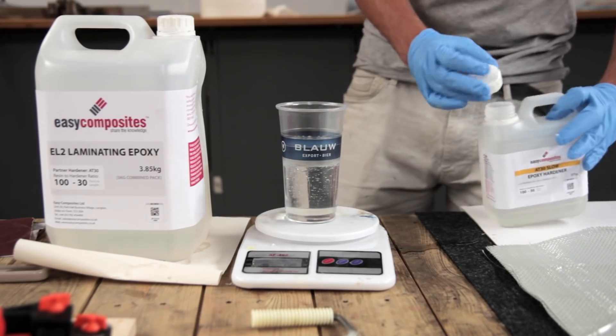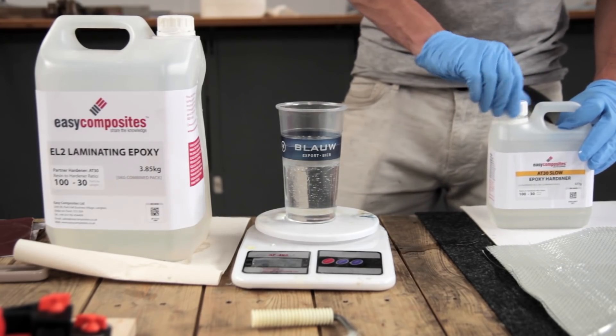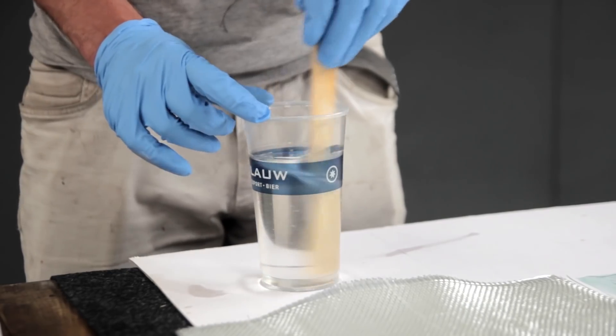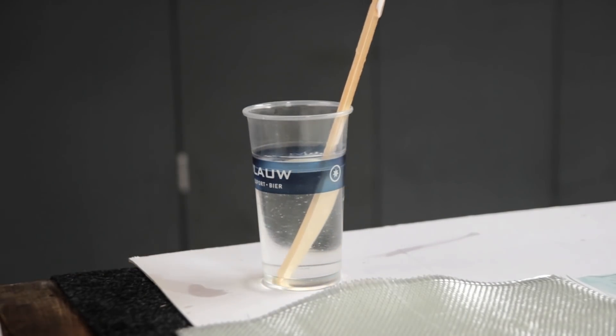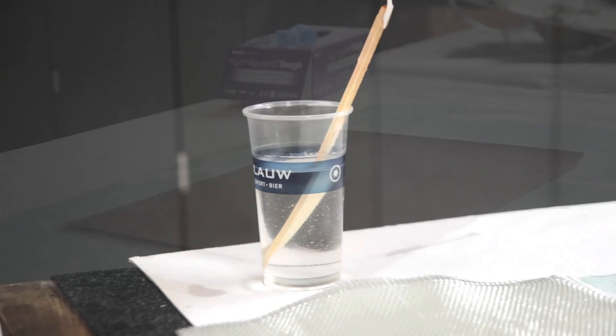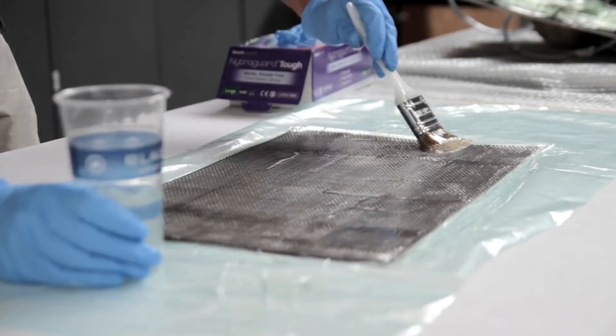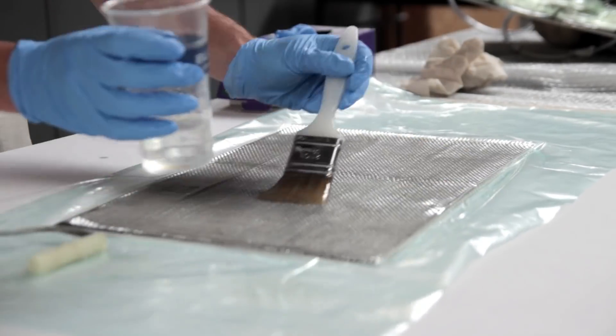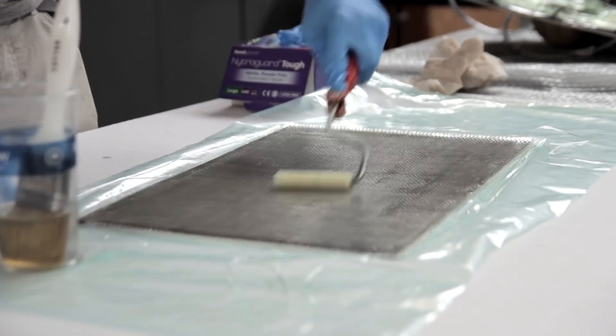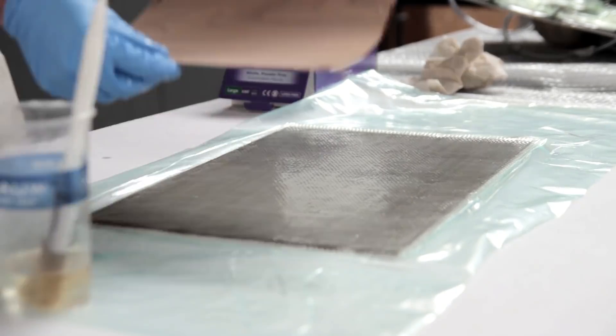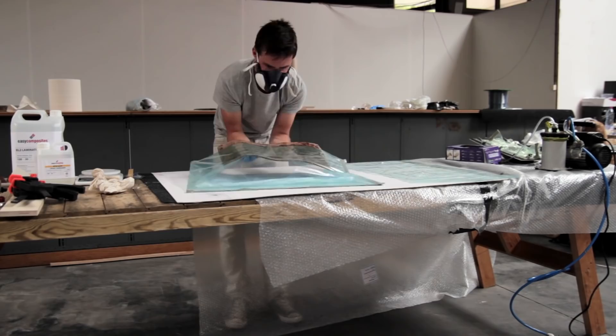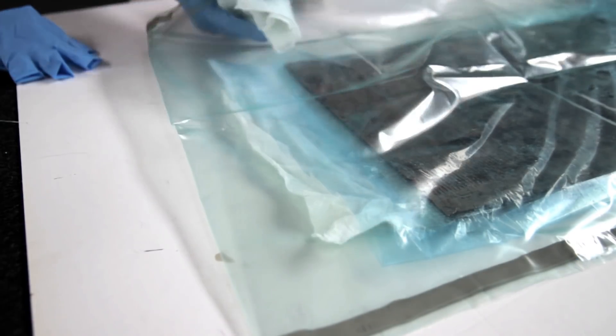I'll be doing it with fiberglass and epoxy resin in between, just to make the strongest stand possible. This is just regular laminating epoxy. I buy it from Easy Composites, you can find it on their website. I'll add the website in the description. Everything is mixed and then I apply it with a generous coat of epoxy with a few layers of fiberglass in between. I use a roller to mix and disperse all the epoxy resin all over the part.